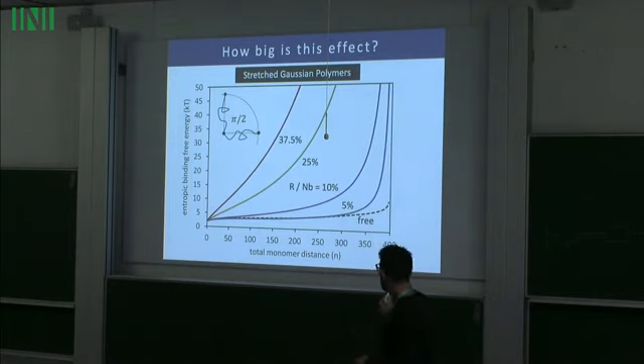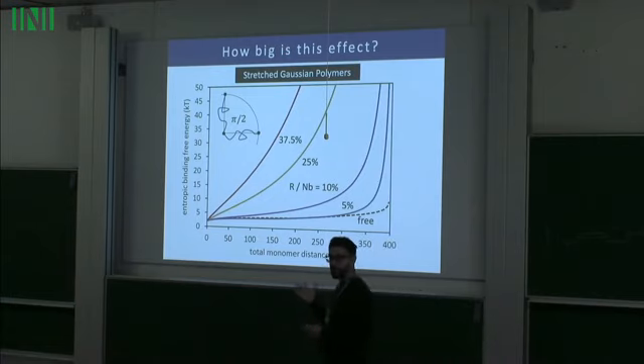Okay. But it is more significant if I look at the case of stretched polymers, or polymers that have their endpoints fixed. And that's actually more realistic for the case that would be happening in a polymer network, where the chains are not floppy, they're actually in a gel as I strain it. Now the chains are being stretched, and they're also attached to other neighbors.